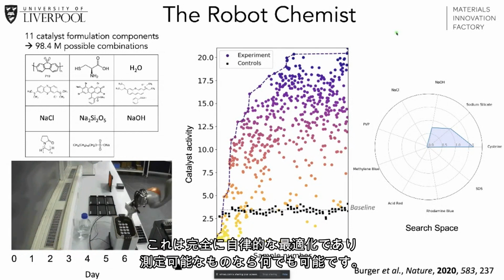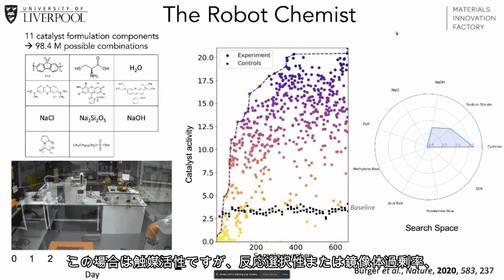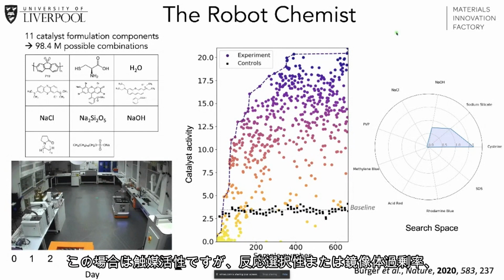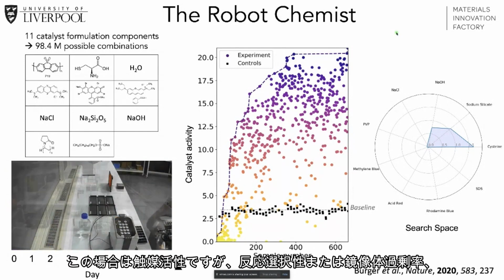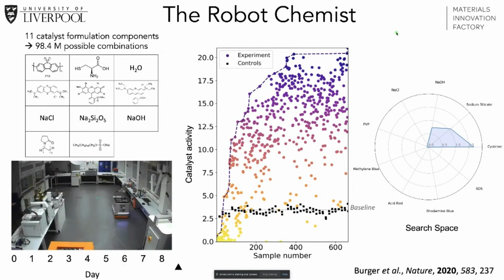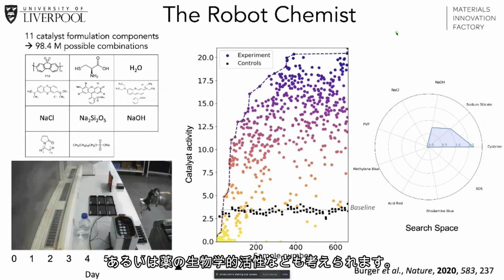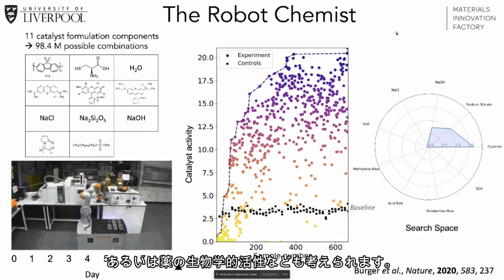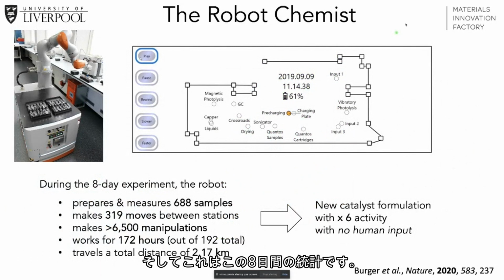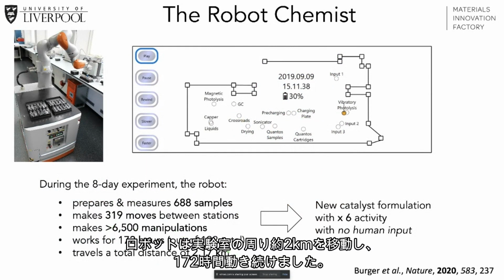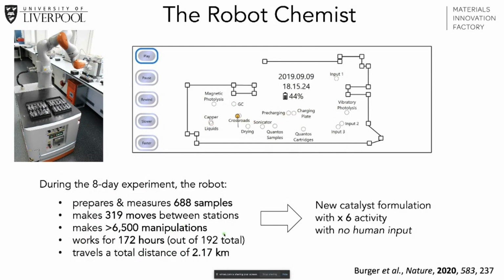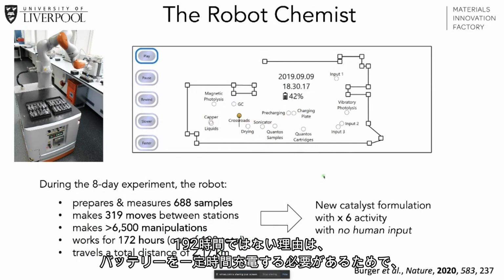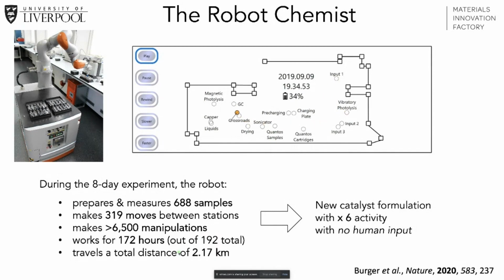And in principle, you can do that with anything that you can measure. In this case, it's catalyst activity, but it could be reaction selectivity or enantiomeric excess, or maybe some biological activity for a drug or something else. And this gives some statistics. Over this 8-day period, the thing travels about 2 kilometers around the lab, and it works for 172 hours. The reason it's not 192 is it has to charge its battery for some period, so it works for about 22 hours a day.